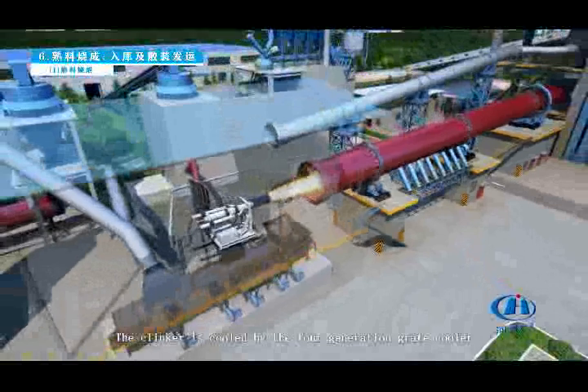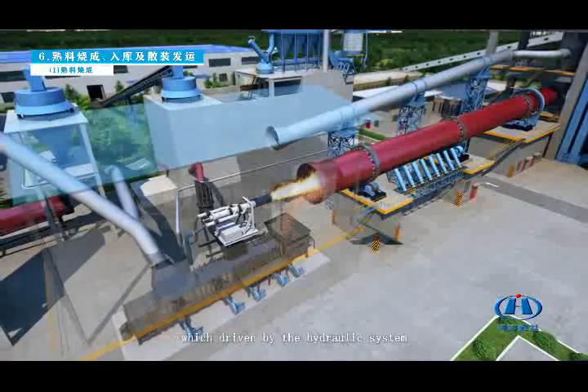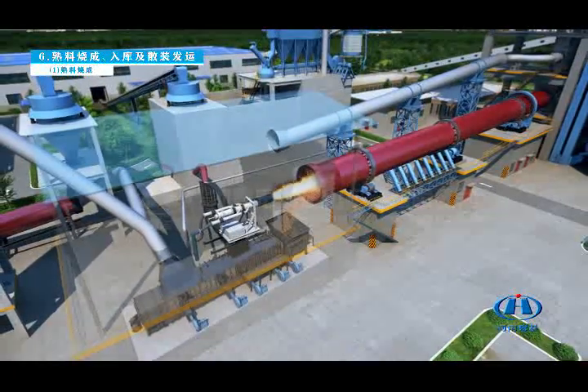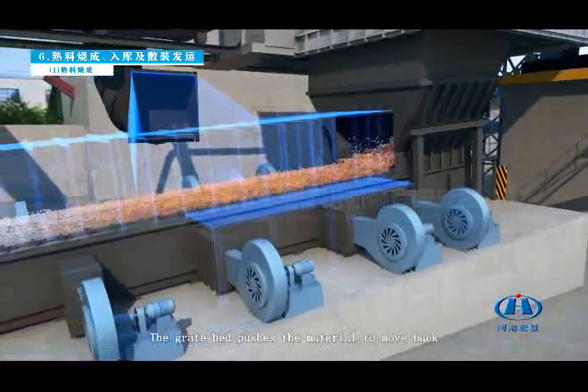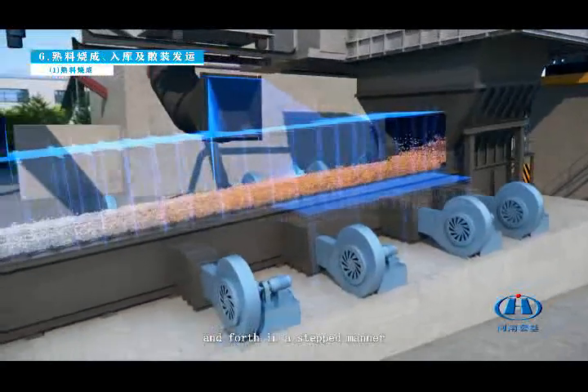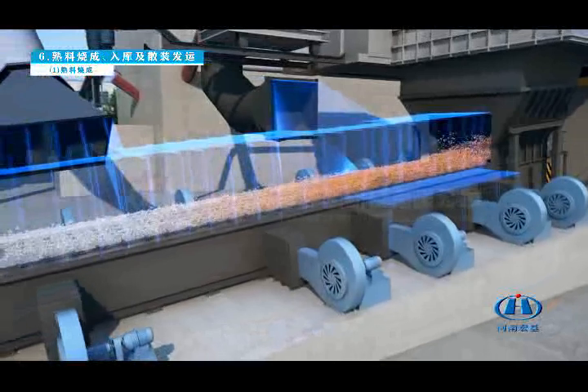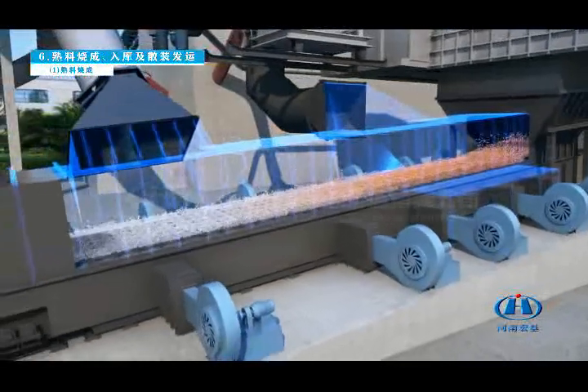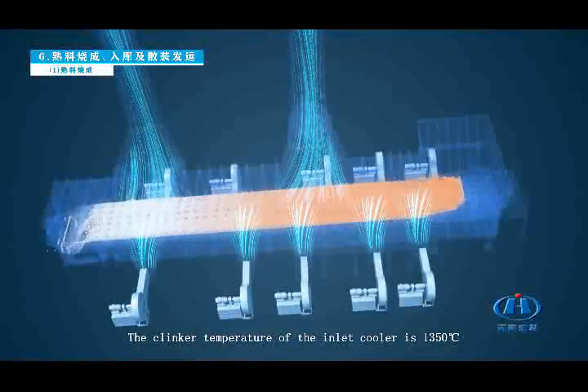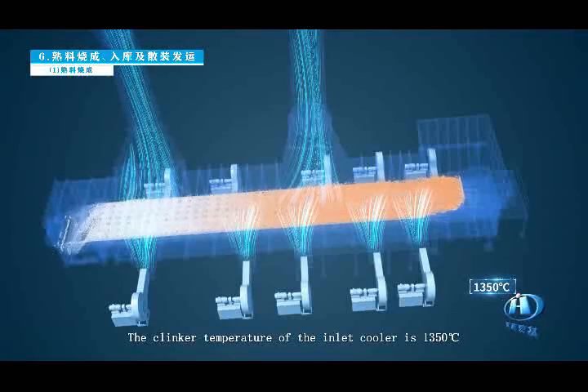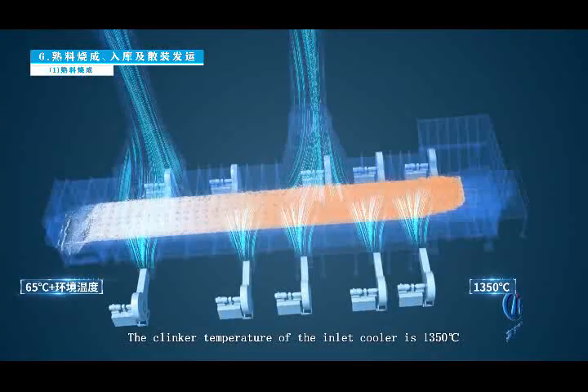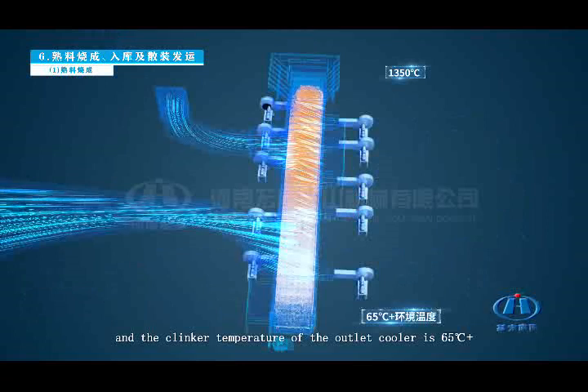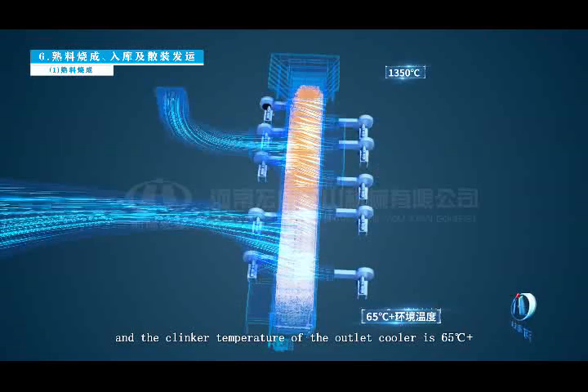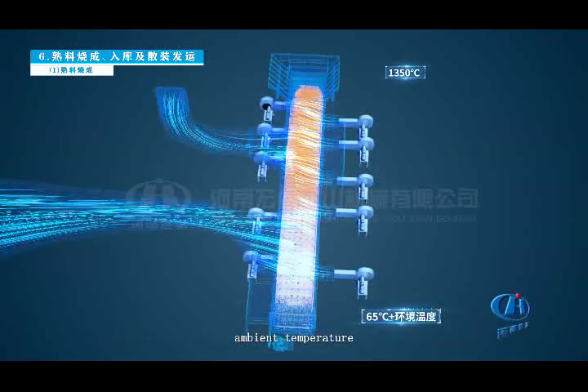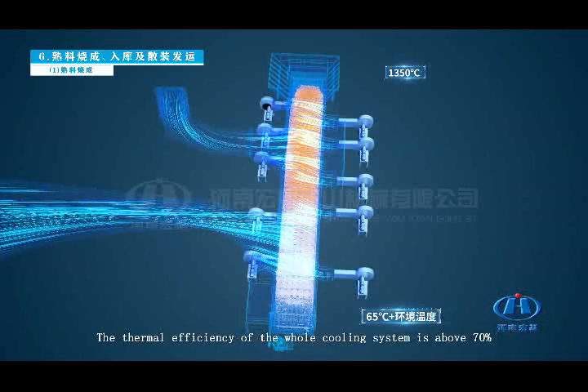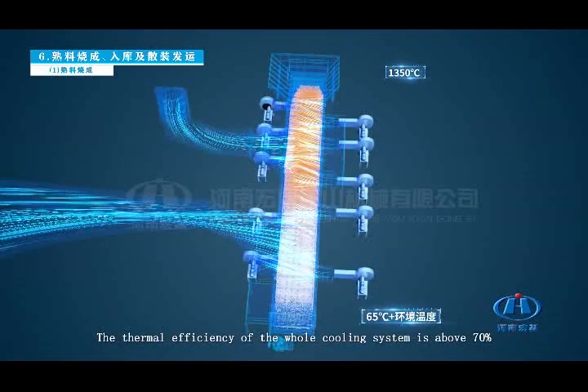The clinker is cooled by the 4th generation grate cooler, which is driven by the hydraulic system. The grate bed pushes the material to move back and forth in a stepped manner. The clinker temperature at the inlet of the cooler is 1,350 degrees Celsius, and the clinker temperature at the outlet of the cooler is 65 degrees Celsius plus ambient temperature. The thermal efficiency of the whole cooling system is above 70%.